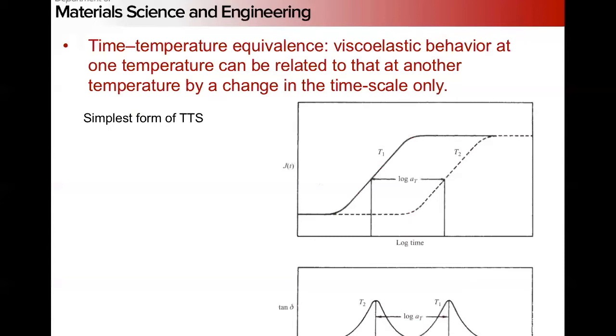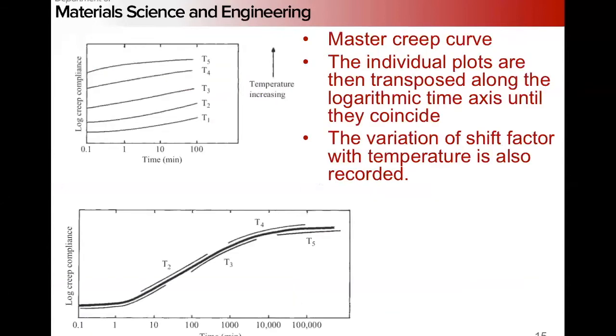So a faster creep deformation at higher temperatures, right? So basically the idea here is we measure the compliance as a function of time for multiple temperatures, right? These curves can then be shifted to where they overlap and plugged together to form a master curve, right? Then, based on the amount that we have to shift these to bring them into coincidence, we know what the shift is going to be as a function of temperature, how we have to move this curve as a function of temperature to get our creep compliance for our temperature of interest, right?